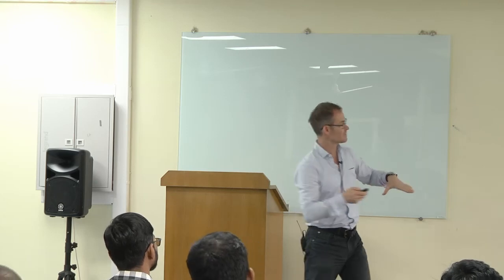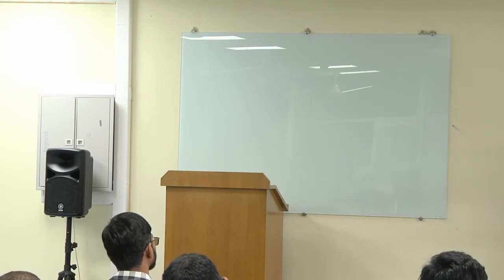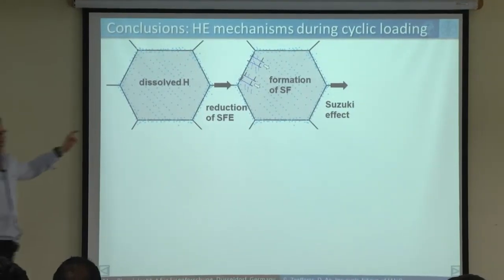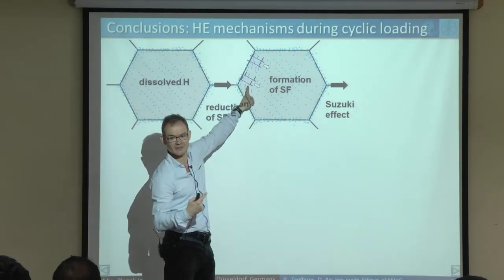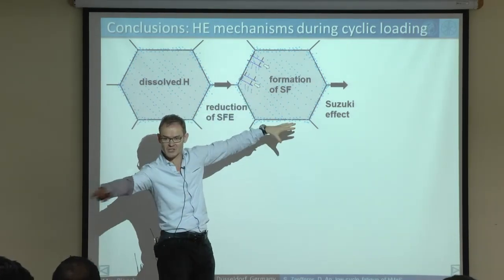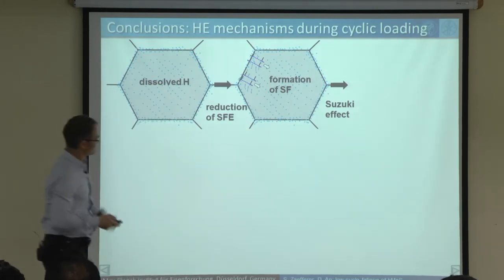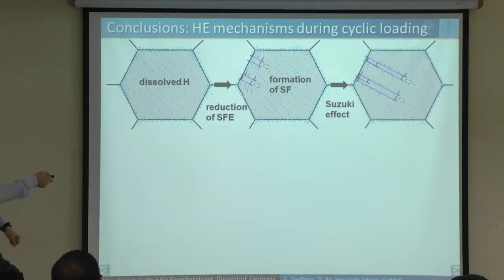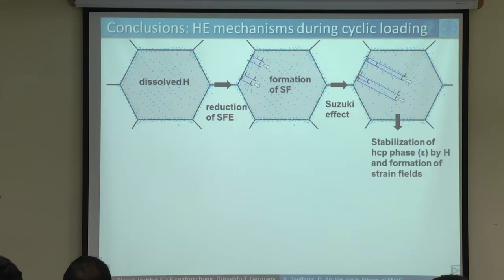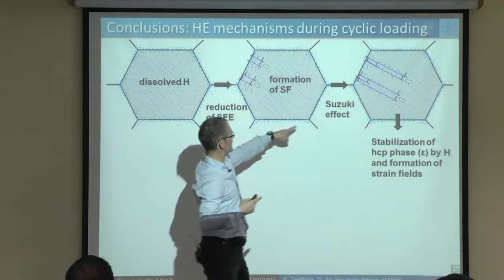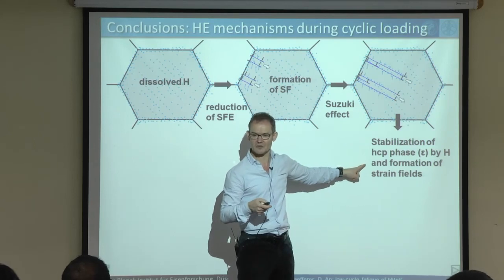Now, the presence of hydrogen leads to a reduction of the stacking fault energy. As a result, all dislocations start splitting up into partials. So you get stacking faults with partial dislocations. This leads now to the Suzuki effect. That means the hydrogen likes to go into these partials because it finds a better surrounding there. So the dislocations split up even more. We get very long elongated stacking faults. Now the Suzuki effect together with hydrogen leads to the stabilization of the epsilon phase.